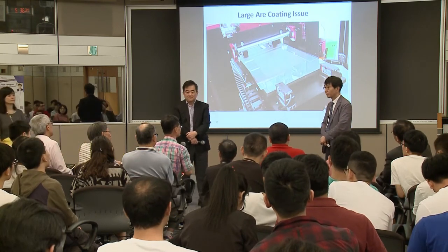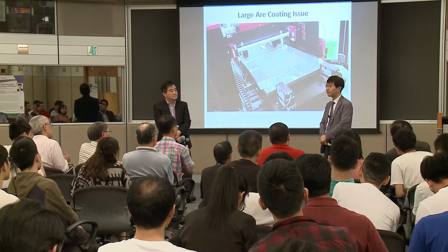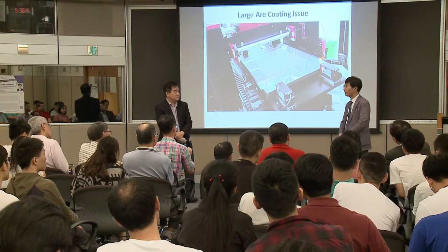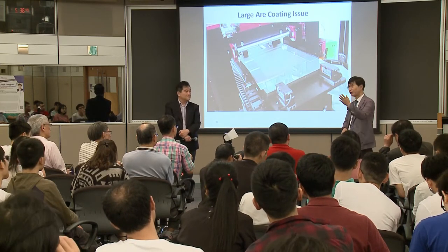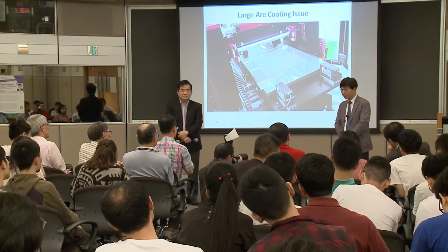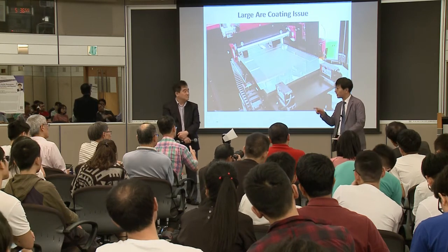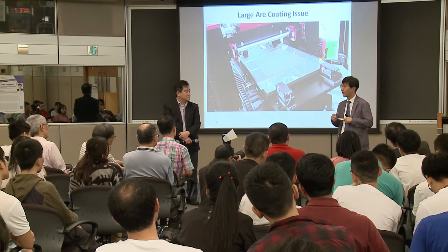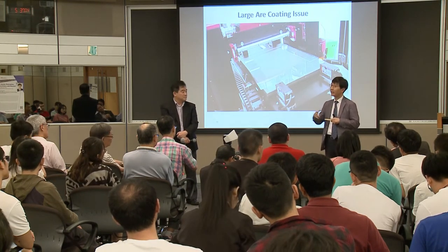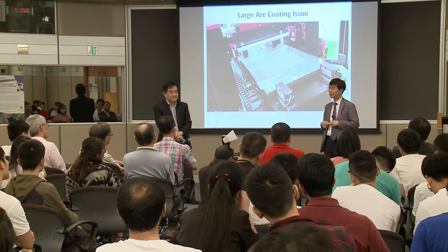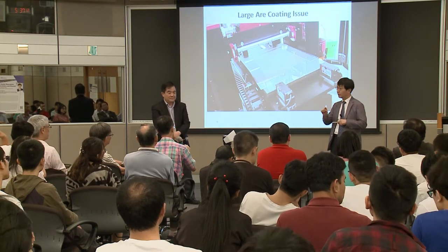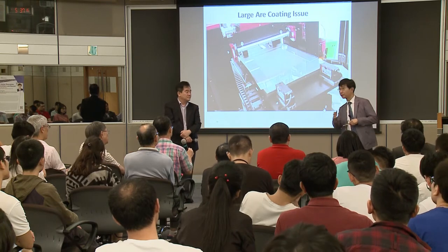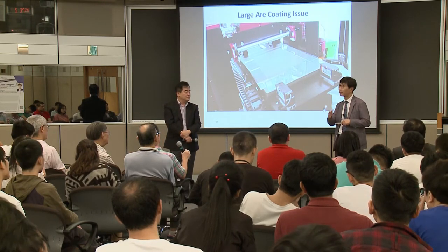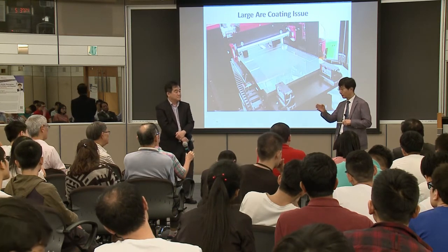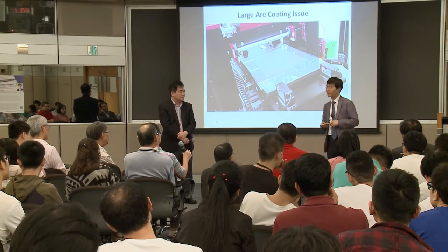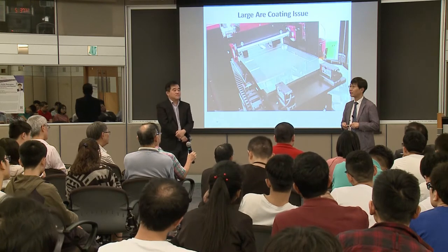How good is the stability to UV? I think the UV stability is okay. We probably have the glass, and the glass already protects from UV. The perovskite material itself is pretty much stable, because even under X-ray and even gamma ray, the perovskite is stable. So under UV light also, the perovskite itself is stable. But if you use glass that can transmit the UV light, or the titanium oxide has some photocatalytic effect, then probably you have some problem in the UV light stability.